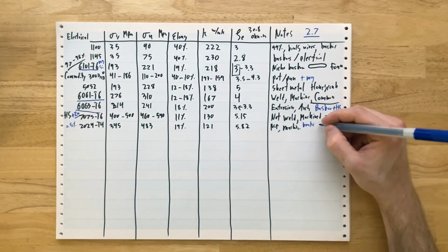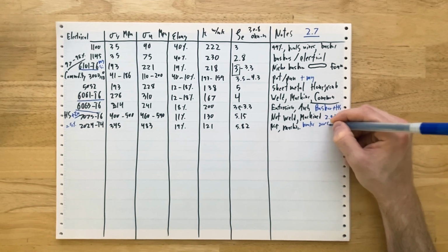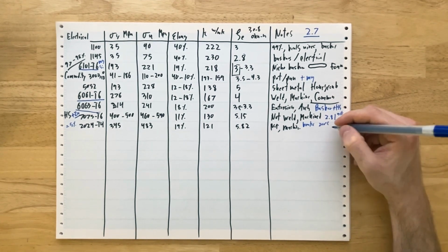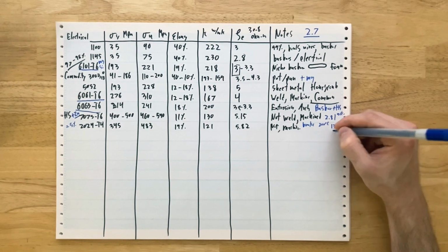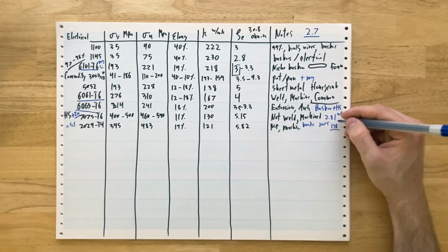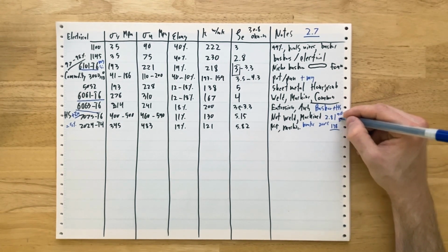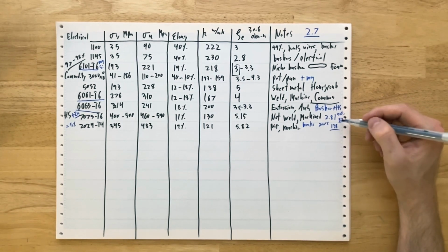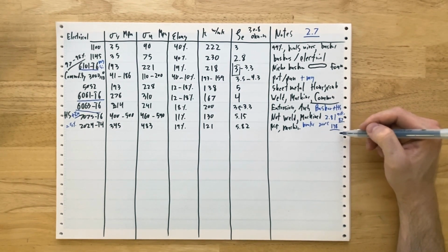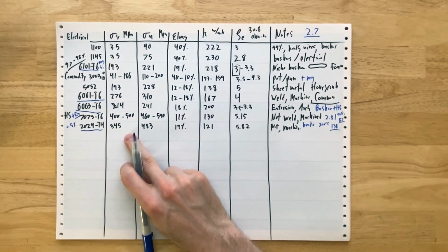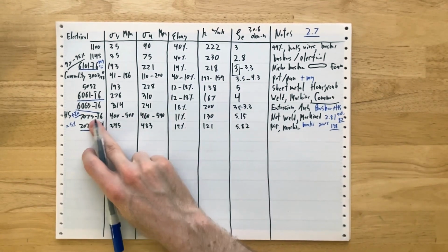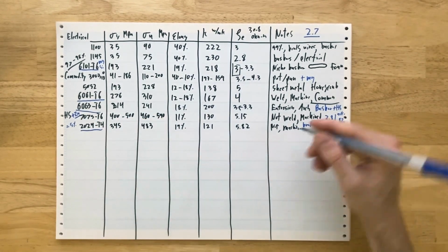So at 200 Celsius, 2024 still has 138 megapascal yield, and 7075 would be down to about 87. So if you're looking for high strength at high temperature, you're gonna go with 2024, even though it's less strong than 7075 at normal temperatures. So that's why it's specifically used in high temp applications.